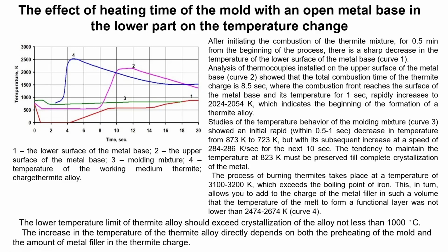The process of thermite reaction takes place at a temperature of 3200 kelvins, which exceeds the boiling point of iron. This in turn allows adding to the charge of the metal filler in such volume that the temperature of the melt to form a functional layer was not less than 2474-2674 kelvins. It's curve 4. The increase in the temperature of the thermite alloy directly depends on both the preheating of the mold and the amount of metal filler in the thermite charge.